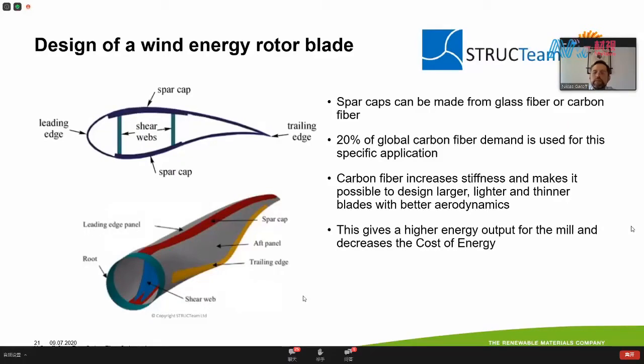Carbon fiber has a big advantage over glass fiber, because it increases the stiffness of the blade, which makes it possible to design larger blades that are even lighter and are thinner, giving a better aerodynamic design. And this in turn makes it possible to either produce more energy per windmill or decrease the cost of energy. So using carbon fibers in the spar caps has big advantages. And actually 20% of all carbon fiber demand goes for this specific application. It's a huge market. So it's about 15 to 20,000 tons of carbon fiber goes for this particular application.